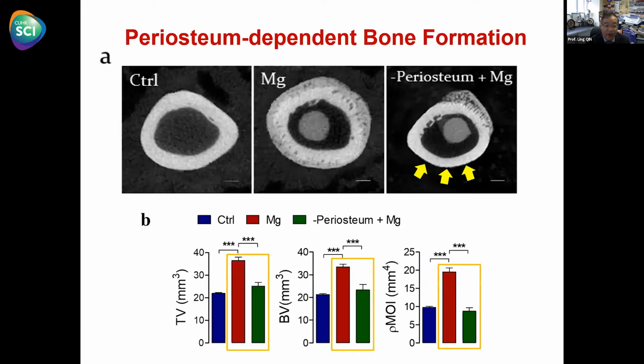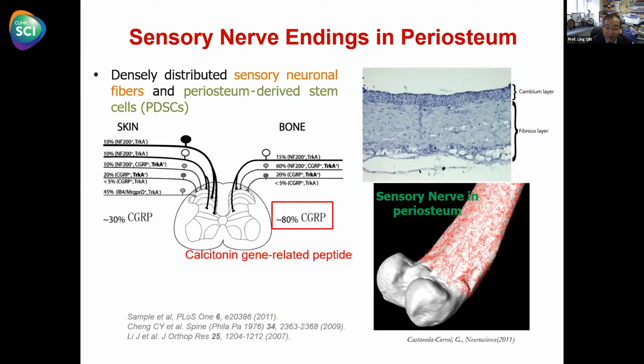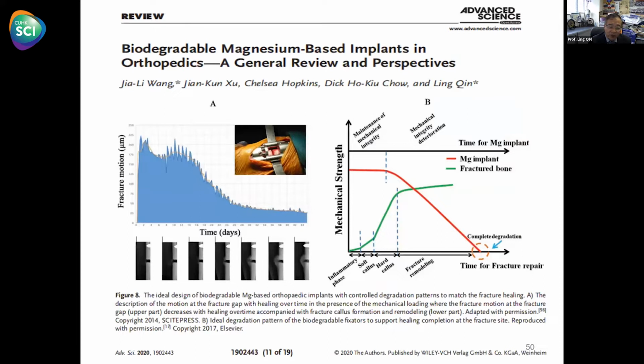We published such a phenomenon. Interestingly, we looked at the bone in the periphery, instead of next to the magnesium degraded parts, and it is active. So what is it? It is the periosteum, the membrane on the bone. After removal of the bone membrane, there is no bone formation, but if one piece is left, you see dramatic bone formation. So what is in the bone membrane? The periosteum has a lot of nerve endings and a lot of periosteum-derived stem cells, and we know stem cells are able to generate new bone. So we can explain such a situation, but if the degradation is uncontrollable, we may have some challenge for real application. That's why, after extensive review, understanding the healing features and degradation properties, we are now developing a hybrid system.